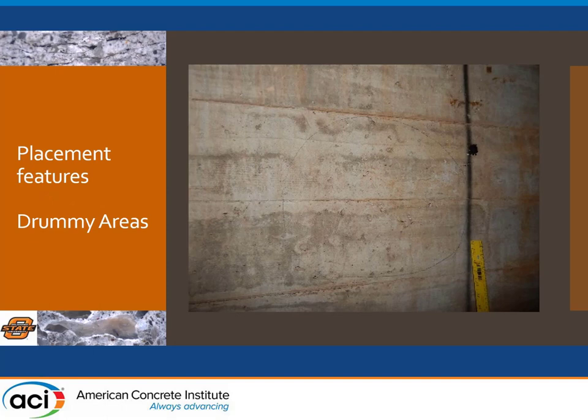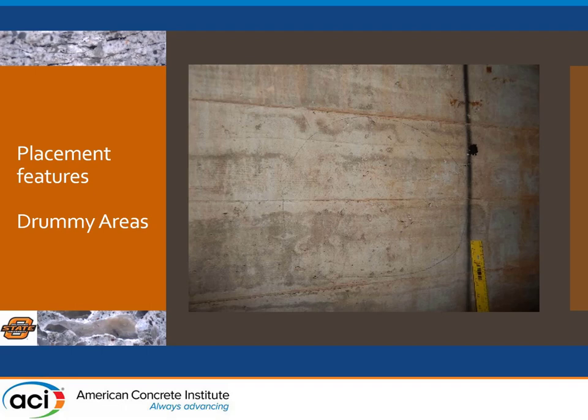Once we got past that extreme initial section and really started walking through the tunnels, the initial glance showed concrete that seemed relatively sound. We weren't seeing salt accumulation, just a few cracks here and there. But through basic sounding, we could hear those drummy areas — those hollow sounds — which led us to start opening up some of those sections. Facilities management gave us the green light: if we wanted to take off concrete, go ahead.